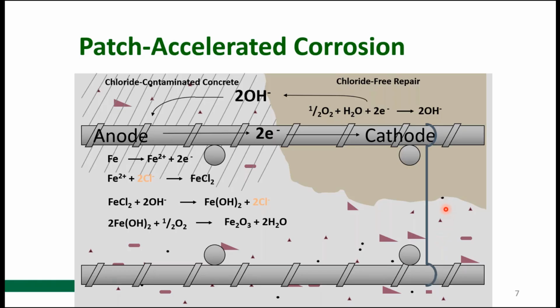Well, it happens because when we do a repair on a deck or a column or a beam, we remove a section of concrete and replace it with chloride-free concrete, but we leave chloride contaminated or possibly carbonated concrete around the perimeter of the repair. And over time, the corrosion will continue, or in some cases even accelerate, in the immediately adjacent area where you've left chloride salt contaminated concrete.